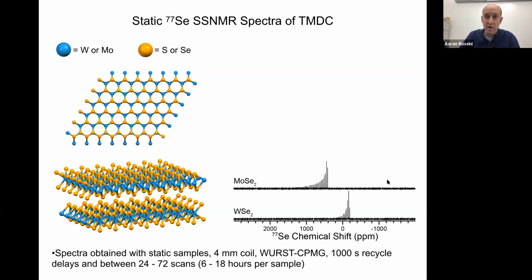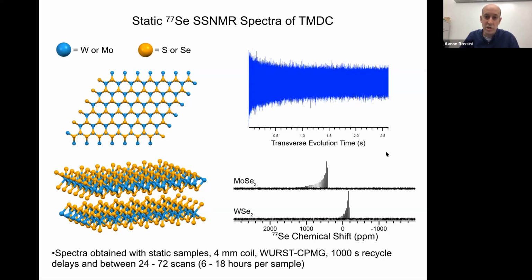So shown down here are the static selenium-77 solid-state NMR spectra, just taken at room temperature. These are acquired using CPMG pulse sequences. CPMG is very efficient here. We can acquire spin echoes for a couple seconds. You have very long T2s, and that gives you a nice sensitivity gain. And you need that because the T1 relaxation times for the selenium are very long. They're on the order of 1,000 seconds. But with CPMG, you only need between 24 and 72 scans, but this still translates to between 6 to 18 hours per sample to obtain a spectrum.